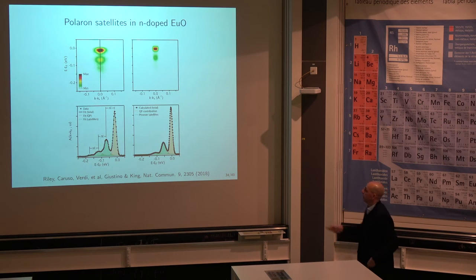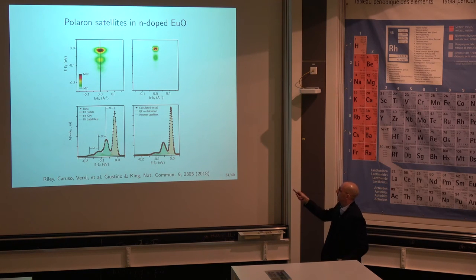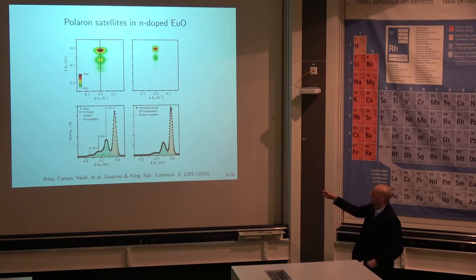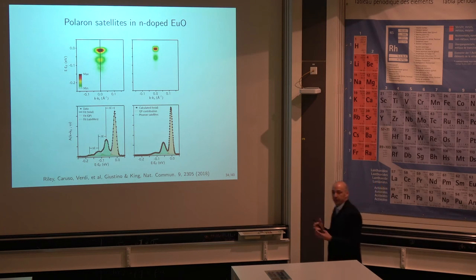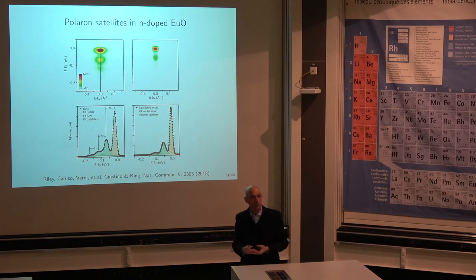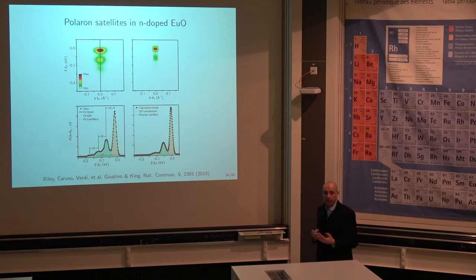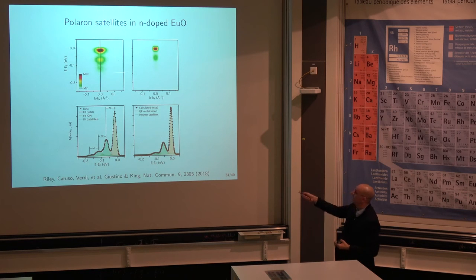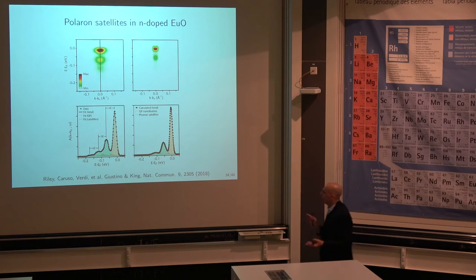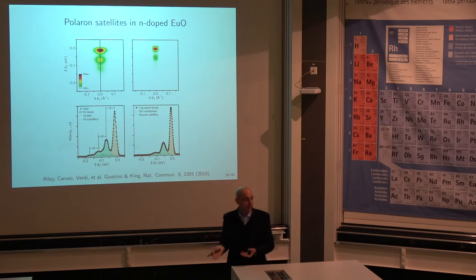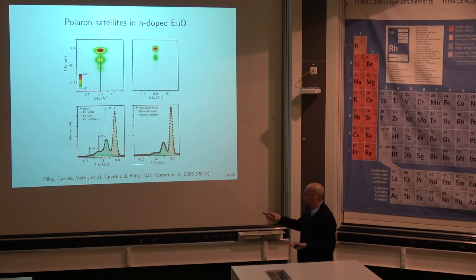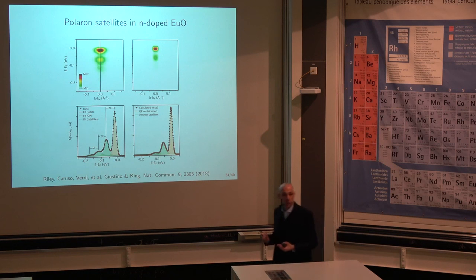So we did calculations for that. This is basically the same picture in the experiment, and this is our calculation. I don't know if you can see properly, but actually there is a satellite also here. Ours is less broad, because we're not including experimental broadening. And also there is a little bit of uncertainty on the determination of how many electrons you have per unit volume, so on the density of electrons. But I would say the agreement is reasonable, and if you take a cut along essentially this k equals 0 here, you will find the spectral function for the experiment and the calculated one. So, if you consider this as an ab initio calculation without any parameters, it is quite impressive to see that both the energies of the satellites and the intensities look quite similar.